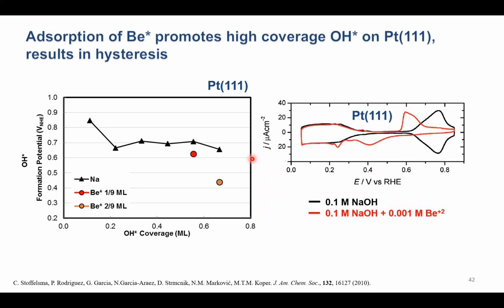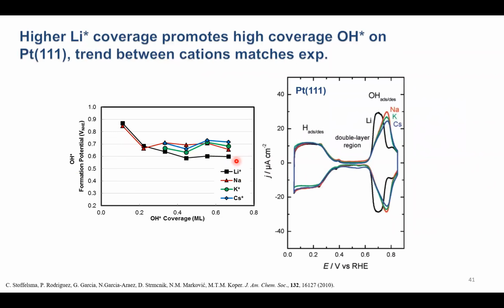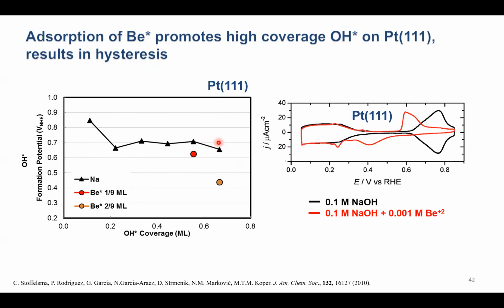And so we looked with DFT at the effects of cations other than the alkali metal cations. In particular, here we're showing work looking at beryllium. Beryllium is one of the smallest cations, with a higher charge to size ratio than lithium. And we see that gives it a larger promoting effect on high coverage OH adsorption than lithium does. So if we have a little bit of beryllium on our surface, we promote OH adsorption a little bit, similar to what we saw with lithium that I went through very quickly. If we have a higher coverage of beryllium, we can promote high coverage OH adsorption significantly, by a 0.3 volt shift here.